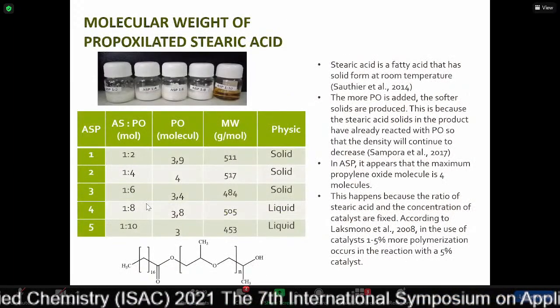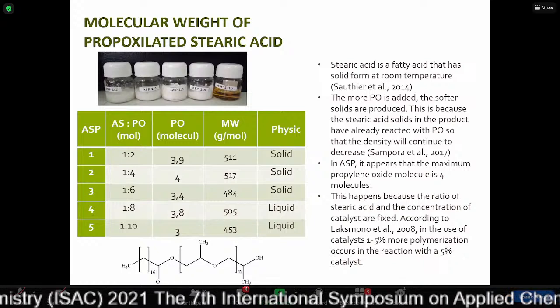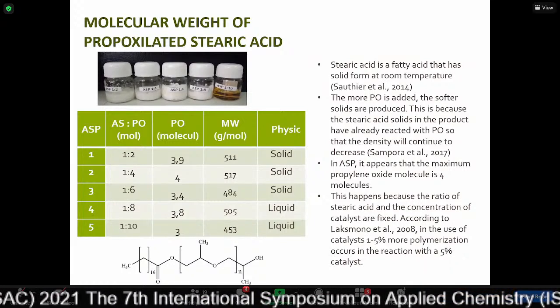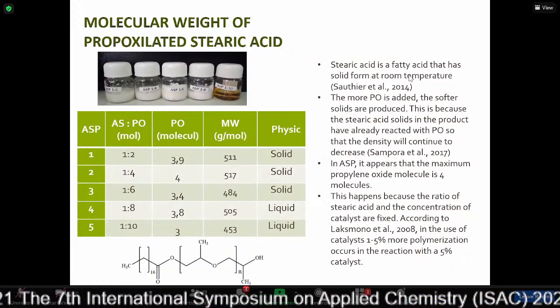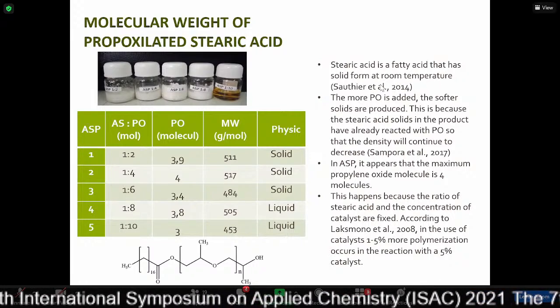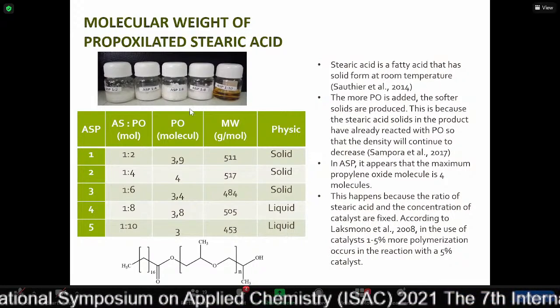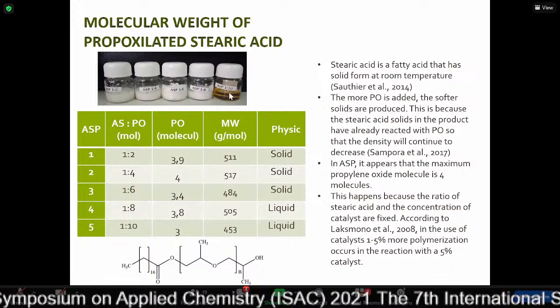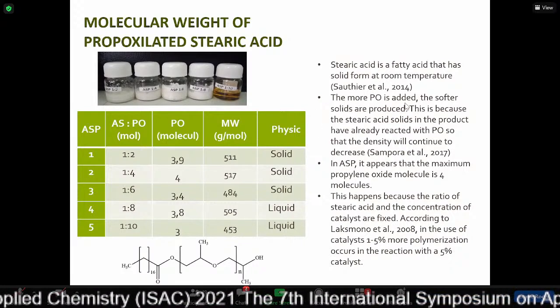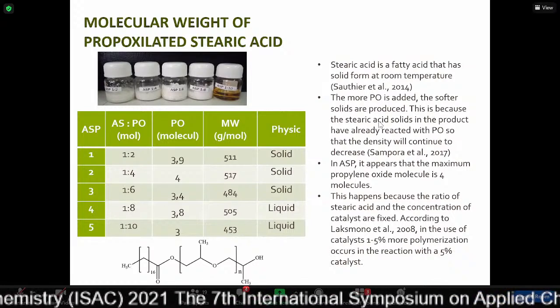This is the molecular weight of the propoxylated stearic acid. We can see here that stearic acid is a fatty acid that is solid at room temperature. We can see from this figure that the more propylene oxide we add, the softer the solid produced.